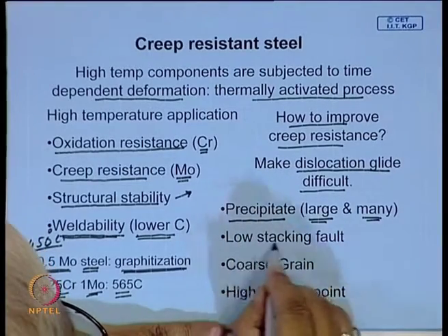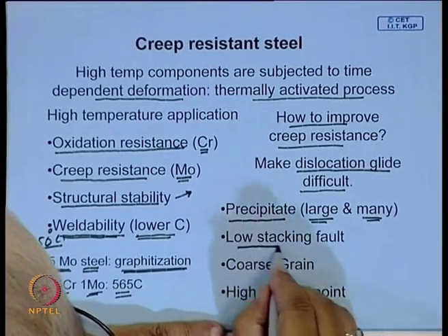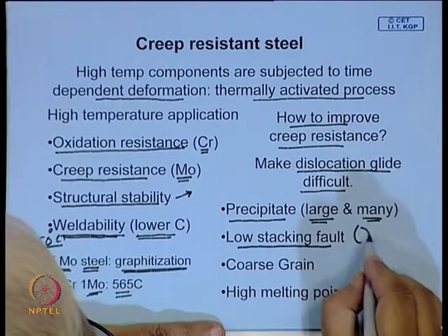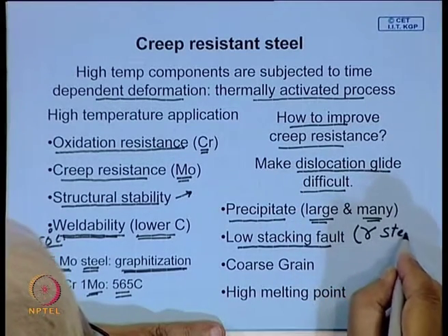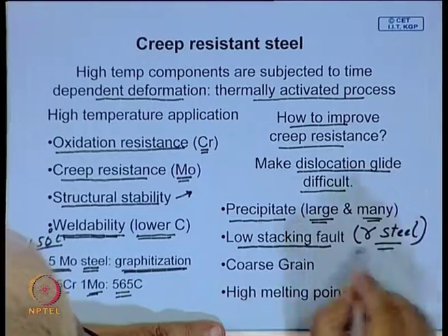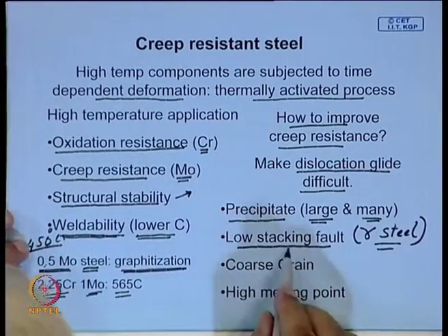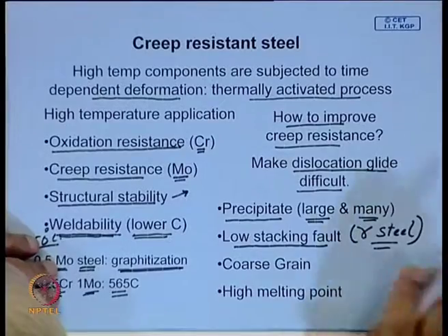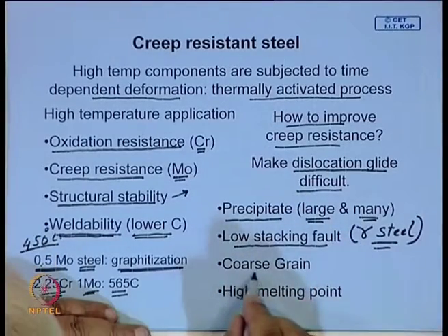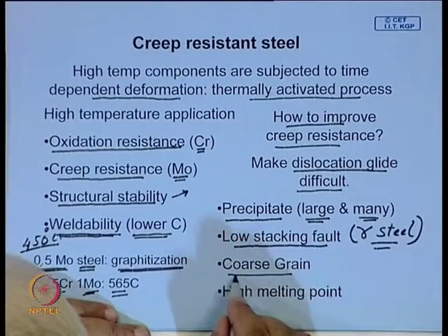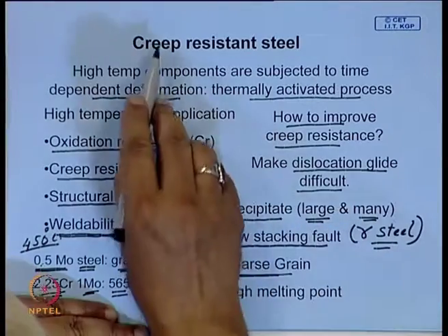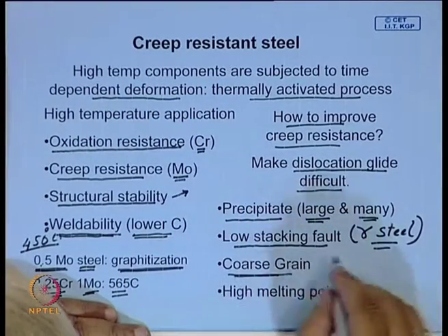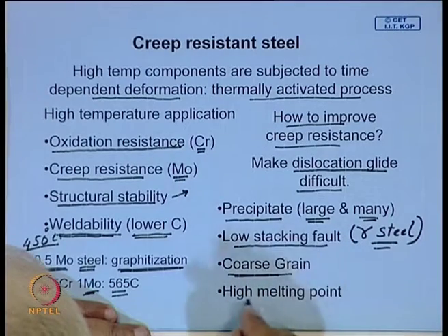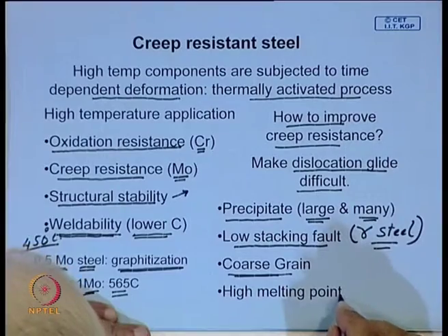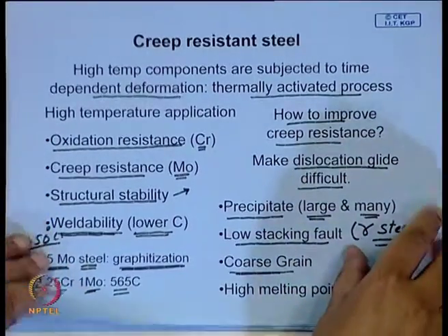Sometimes you can make dislocation movement difficult by lowering stacking fault energy, like austenitic steel. They have low stacking fault energy. So, therefore, screw dislocations cannot cross slip, and movement will be difficult. Then another important factor is coarse grain, and obviously, when you are looking for creep resistant steel, anything working at a high temperature, you will definitely be looking for a material which has high melting point.